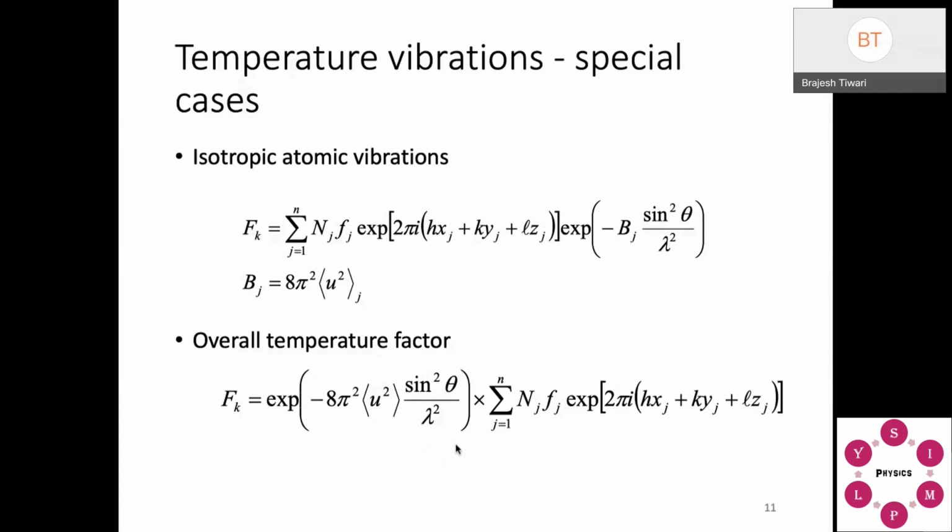So better you always choose smaller angle peaks for determining your particle size if you are just using the Scherrer formula. If you go for higher angle, that will be trouble. You are going to get the wrong value of particle size, or crystallite size.